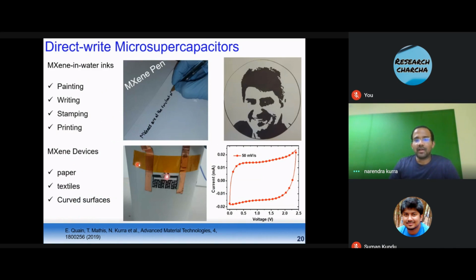And also, given the tunability of the rheological properties of MXenes, we can develop MXene inks, and they can be readily filled into pens to make MXene pens. And when you write something, these are conductive MXene patterns. And of course, the ink characteristics are such that we can even replicate fine features. This is the main advantage: the rheological properties of the MXene ink enable us to make fine features without smearing effects. And again, we can also demonstrate that we can directly write or make devices on curved surfaces, because it's a single step process. And a series connected device can light an LED and act like a micro power source.